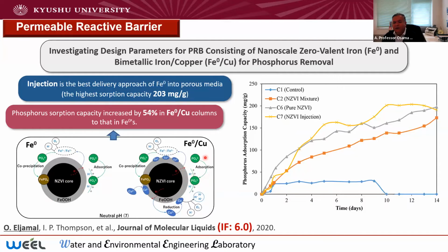We here apply different iron nanoparticles, which is iron with copper, and we call this one iron copper bimetal. So we clarified all the mechanism to remove the phosphorus from groundwater through this study, and we found that the injection is the best way to deliver the iron nanoparticle into the system to remove or to recover the phosphorus from the system.